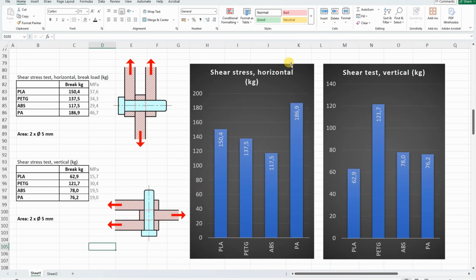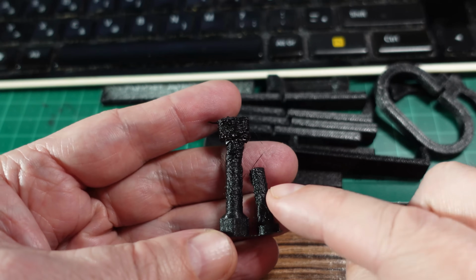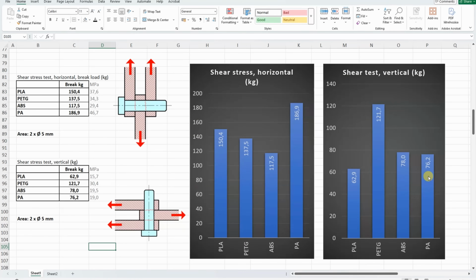When printed in horizontal position, fibers always help a lot here, and fantastic value from the PA or nylon. Now printed in vertical position, the layer adhesion is very important, and fantastic value from the PETG. Now PA, this could probably be even better, but remember that because of that minimal layer printing time, which was too short, I have very ugly last 2 vertical test objects, but without any further drying, I didn't want to invest more energy into this.